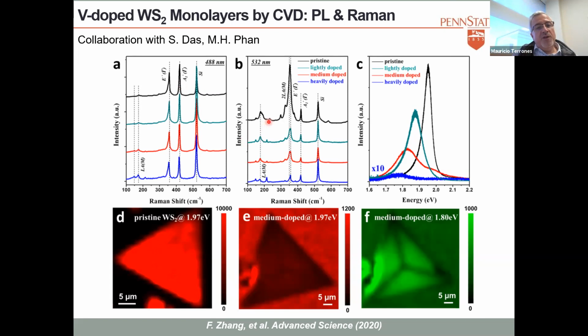So one thing we noted when we use the green laser is that as soon as we start putting some vanadium, this resonant peak, which is the E prime mode, starts decreasing in intensity. So that means we are really affecting the lattice. So the in-plane vibration has been affected, and the signal, and the ratio of these two peaks, is also affected. And then we can see the LA mode, and then you can see another sort of peak coming here from the defects.